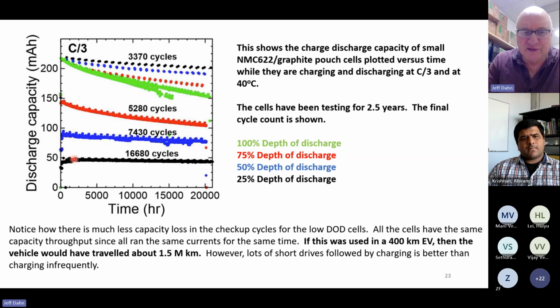But every roughly 500 hours, in all cells, we do a 100% depth of discharge, so-called checkup cycle. And you can see that when you're cycling over the 25% depth of discharge range, every time you do a checkup cycle, you get way better capacity retention than if you were doing 100% depth of discharge every time. And the same is true for 50 and 75. It's better to do these repeated small depth of discharge cycles as opposed to a lot of 100% depth of discharge cycles.